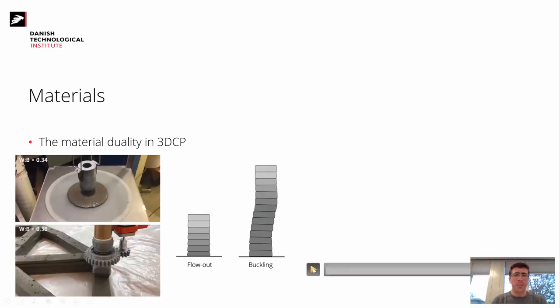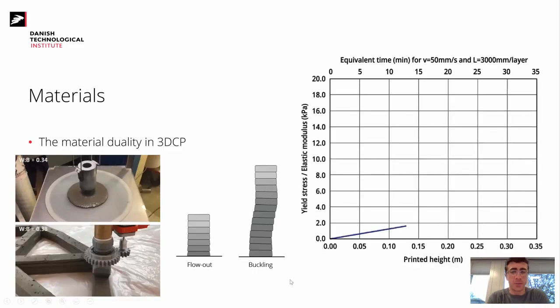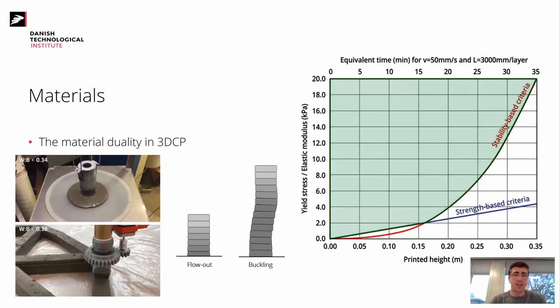So this competition of physical characteristics of the material is roughly translated into two properties. One of them would be yield stress of the material, so how much shear stress you have to put into the material so it starts flowing. And the second would be elastic modulus, which is more relevant to the buckling of the layers you are printing. So if you look at the chart, if you are somewhere within the green zone, you prevent the two failures from happening, the flow out and the buckling.